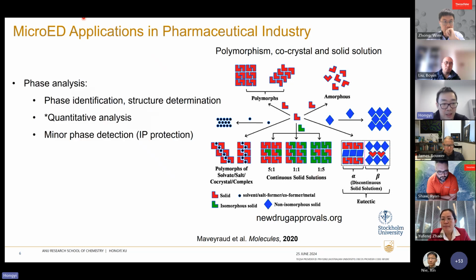And basically, we can do phase analysis. We can do phase identification. So if we have a powder of mixed polymorphs, we can take this powder and treat each small crystal as an individual single crystal, and then do phase identification. And if it's a new phase, we can even do structure determination. Right, we also want to do some quantitative analysis. I put the star here because this requires very rigorous, robust sample preparation and data collection protocols. So really, before we can go to high throughput, quantitative analysis will be quite difficult for MicroED because we only look at a very small amount of the sample.